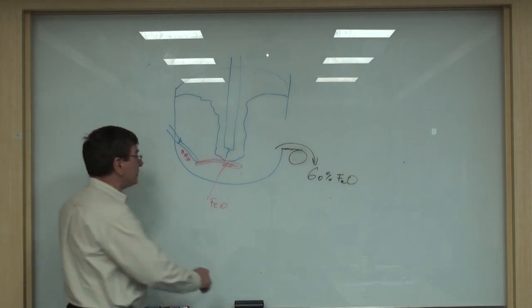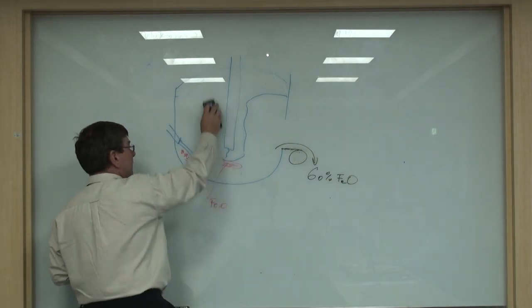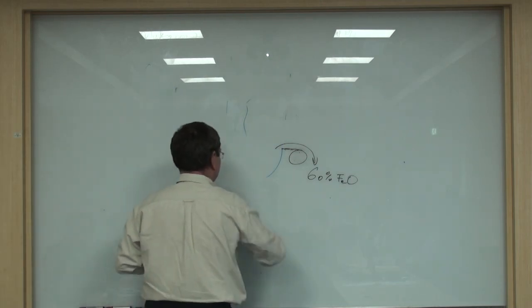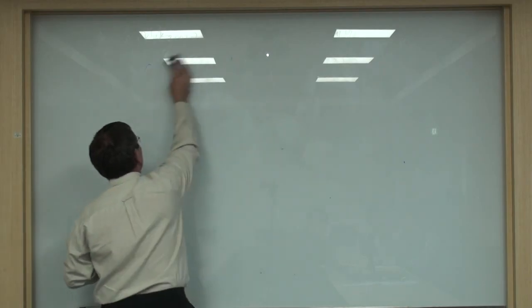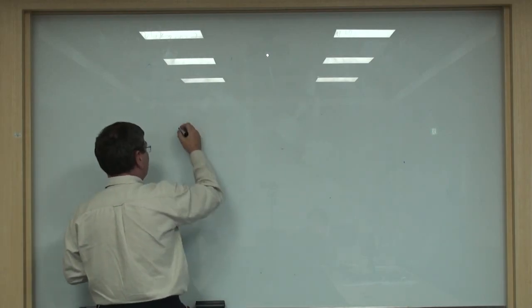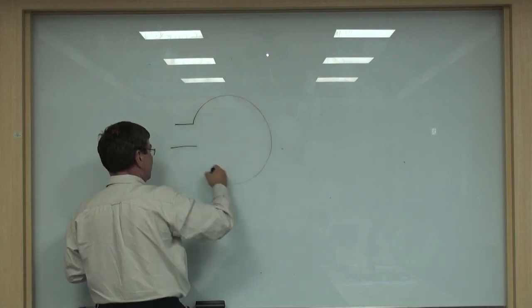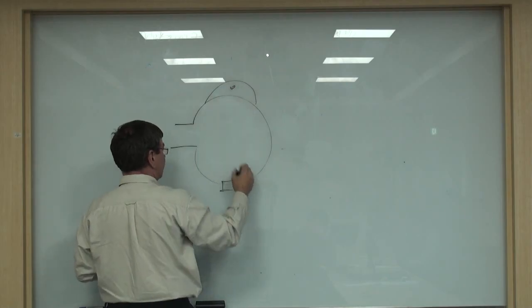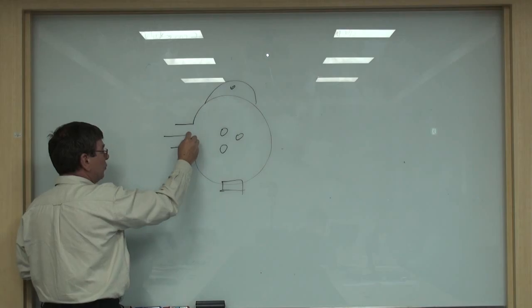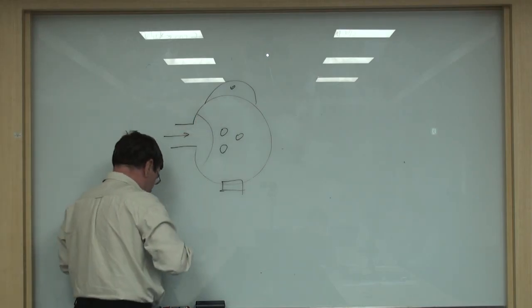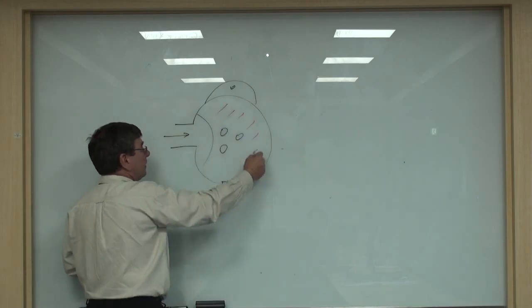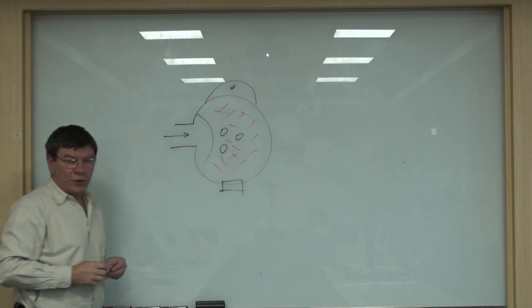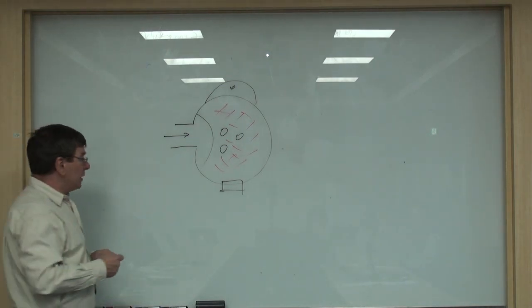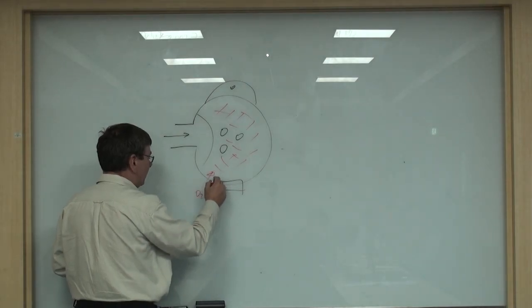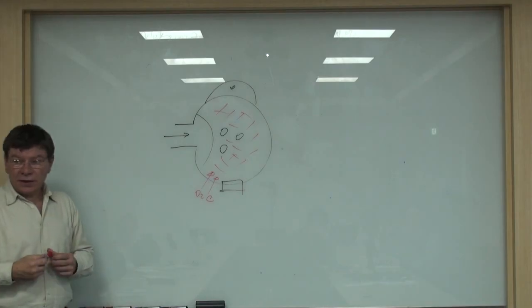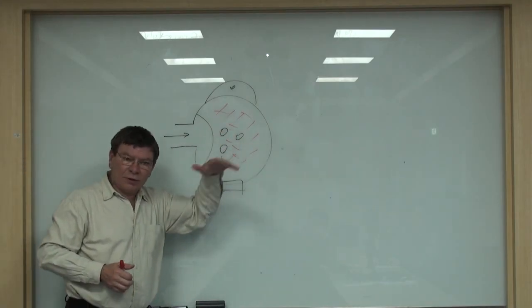Why? Because the scrap is brought by the side. Okay, I will draw another one. This is the furnace. Scrap is brought by the side here. So this area is free for the hot heel and liquid slag. That means if you start injecting oxygen and carbon, they can react in the slag. And the slag remains all the time of the heat with low FeO.